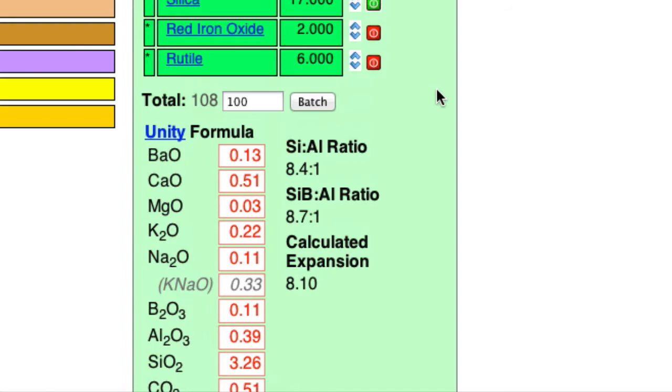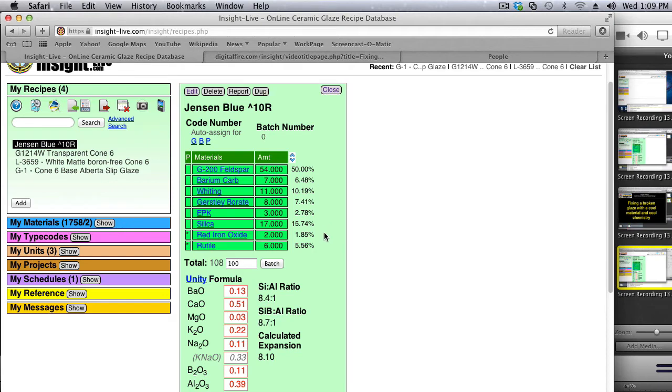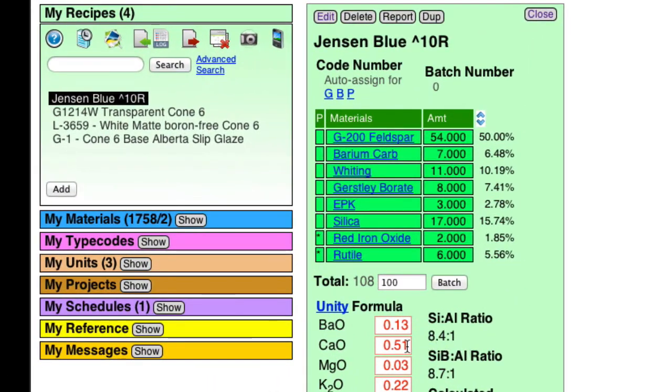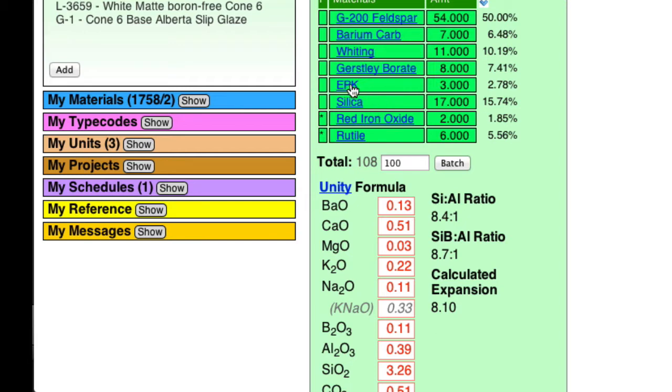There's just so many ways to improve this glaze. But I'm only going to do what is practical right now. I'm going to leave the crazing and the barium leaching issues for now, assuming it's non-functional. But I need to supply the CAO, the B2O3, and the BAO from non-gassers to reduce the blistering and the pinholing. And for the slurry and drying issues, I need kaolin, EPK.